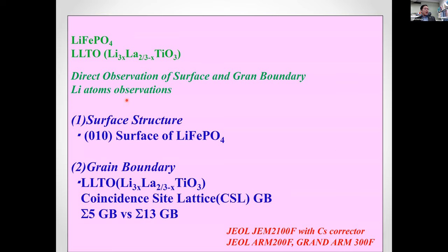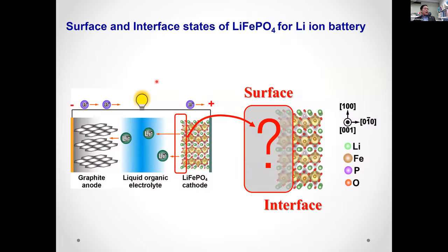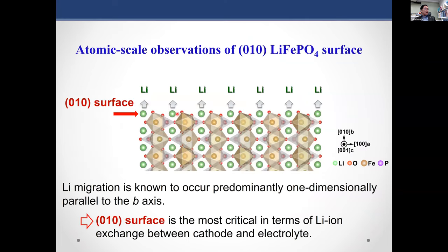Okay, first I will show the surface structures of the olivine. That is the 010 surface of iron olivine. This surface is very important. I have already shown this schematic. As I told you, the dissociated interface is very important. This 010 surface, the b surface, is very important because lithium, indicated by green color, is known to migrate one-dimensionally, parallel to the b axis. Therefore, this 010 surface plane is very important for understanding lithium ion exchange.